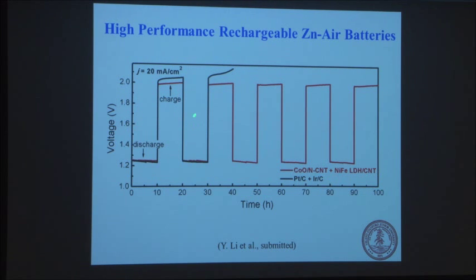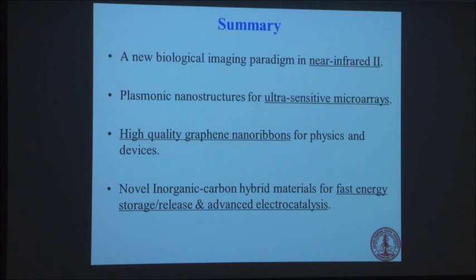And the thing to note is this potential difference here. The smaller, the better, okay? Because that means your overpotential would be the smallest. So this overpotential we're getting here is actually one of the smallest reported in literature because of the activity of the catalyst. Okay, even though there is still a 0.8 volts difference, but that's the best we can do for now. Anyway, so that's the end of the talk.